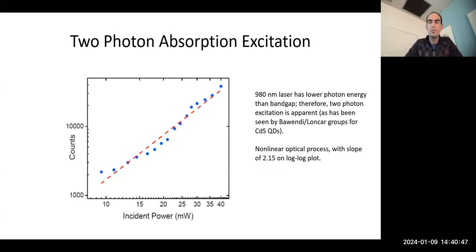I mentioned we used 2-photon excitation. To prove this, you'd expect the power of emission to scale as the square of the incident power, since you're absorbing 2 photons. So if you double the intensity, you expect 4 times as much emission, and that is indeed the case - or you require double the intensity to obtain that.